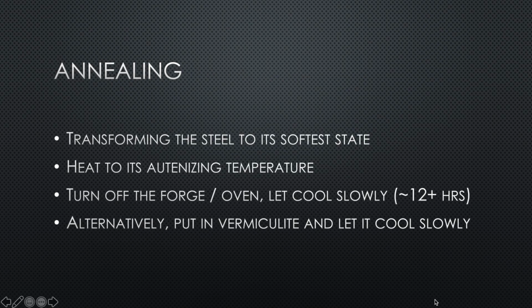So what this does is transform the steel to its softest state, and this is what you want for grinding or things like that. In order to do this, we're going to heat it to its austenitizing temperature. If it was 1095, for example, you would heat it to 1475. We turn off the forge or the oven and let it sit in there and cool slowly as the forge or the oven cools, usually 12 hours. Alternatively, if you want to keep using your forge or your oven, you can place this in a big bucket or steel canister of vermiculite and let it cool slowly.